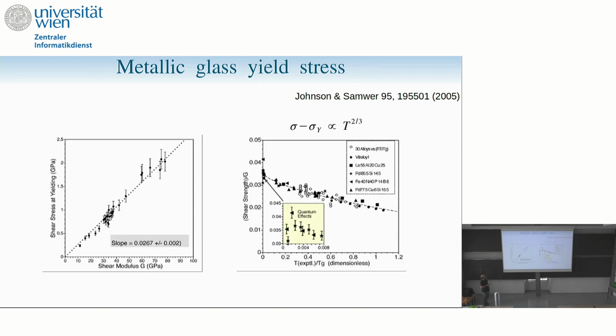And this is really metallic glass data, and so you see that temperature causes a change of the yield stress, which is down much below the glass transition temperature. So the yield stress is sensitive to temperature, even when you are looking at the flow of a solid. All right?